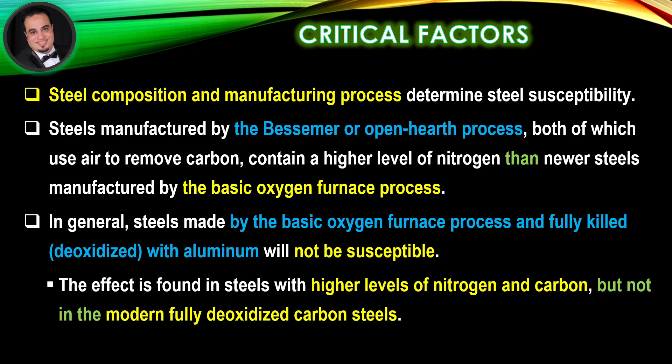In general, steels made by the basic oxygen furnace process and fully killed — deoxidized with aluminum — will not be susceptible. The effect is found in steels with higher levels of nitrogen and carbon, but not in modern fully deoxidized carbon steels.